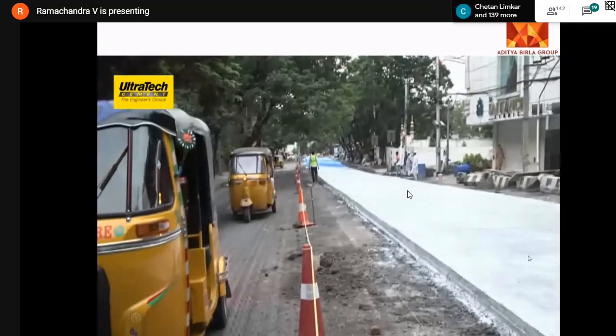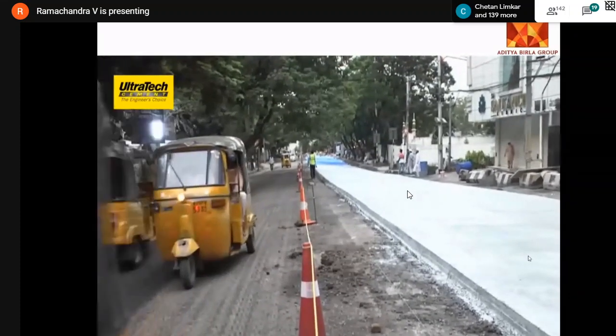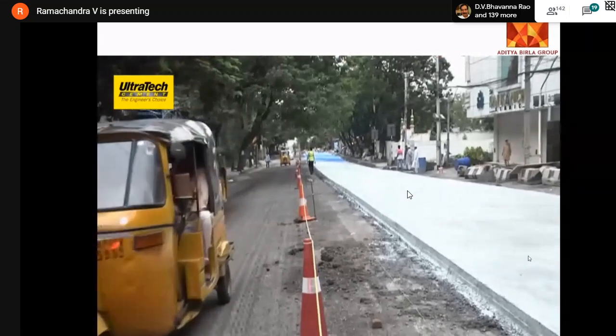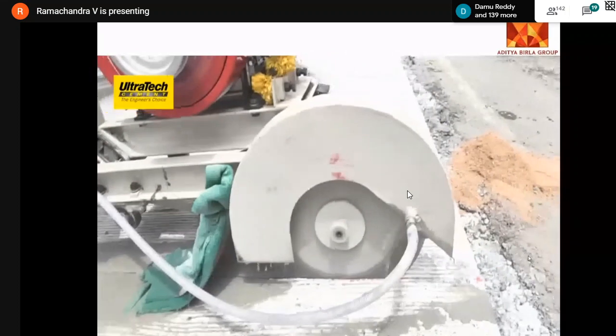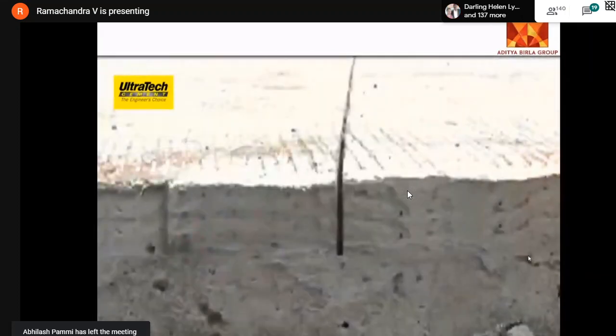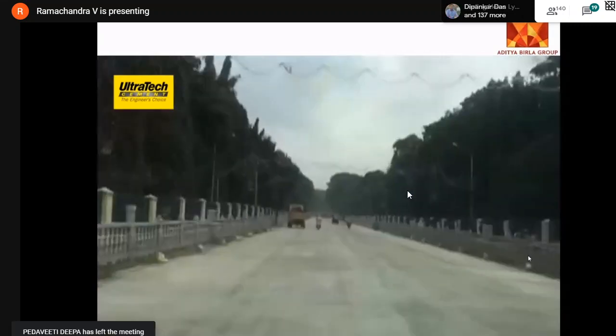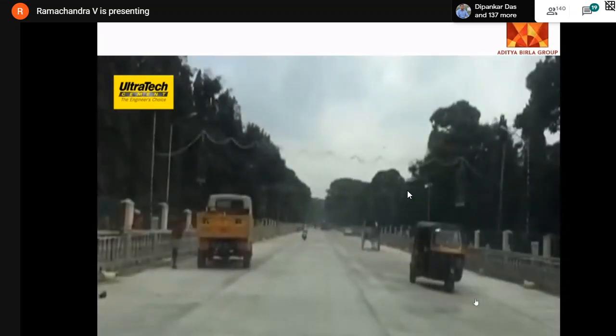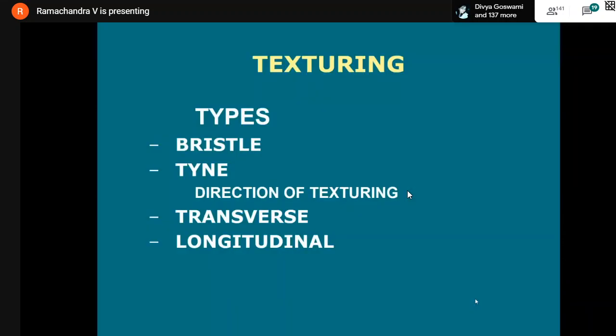Texturing can be done either manually or mechanically. Once the texturing is completed, and when concrete starts stiffening, a layer of curing compound is sprayed uniformly on the surface and on the sides of the concrete. After around 8 to 12 hours of concreting, the pavement grooves are provided to a depth of 1/3 depth of concrete. Traffic can generally be allowed on the surface after 7 days. Yes, that is called as the slip form paving.